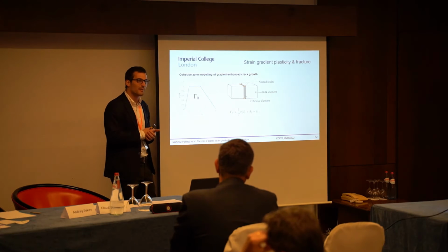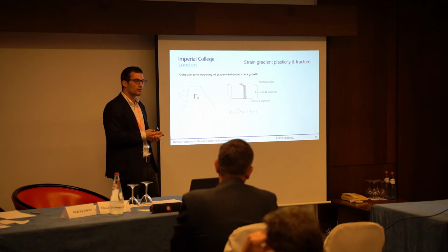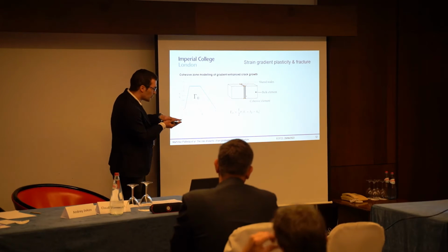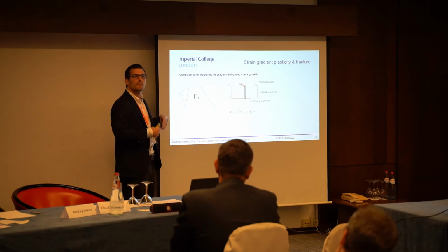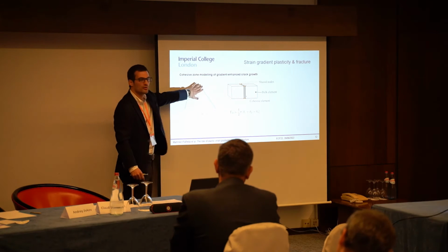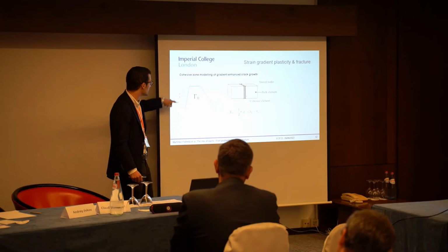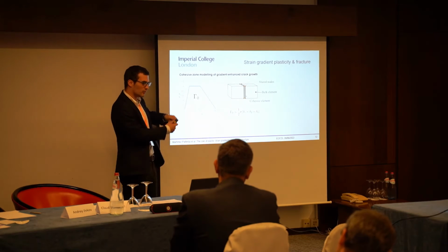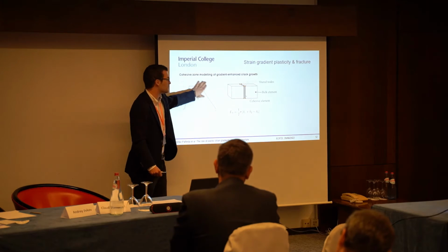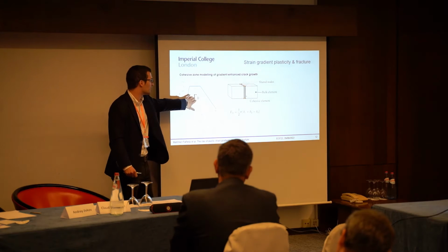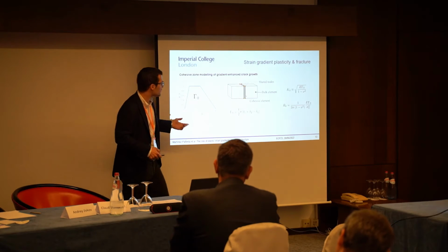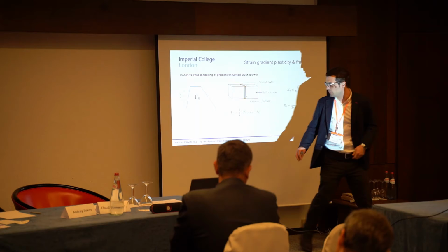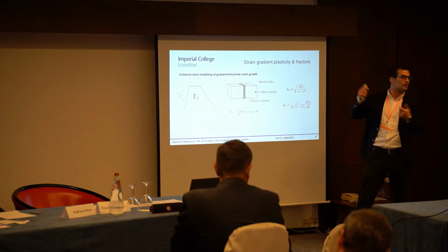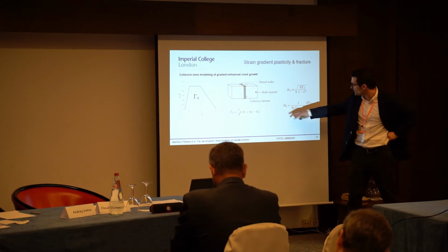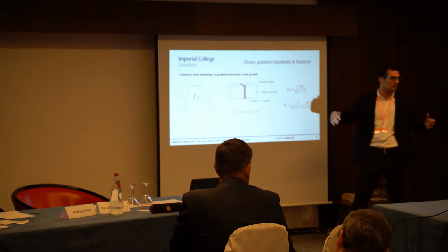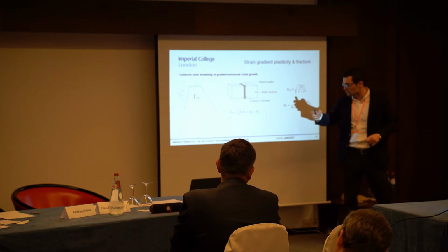So we tried to do a more systematic study. For that, we decided to model crack growth. So we placed some cohesive elements ahead of the crack. Those cohesive elements are characterized by a traction-separation law with two key ingredients. One is the cohesive strength, and then the other one is the fracture energy, which is the area under the curve, this gamma naught. And based on this fracture energy, you can come up with two variables. One is the reference stress intensity factor at which cracking will initiate, and the other one is the size of the fracture zone or the plastic zone, which again scales with this fracture energy.